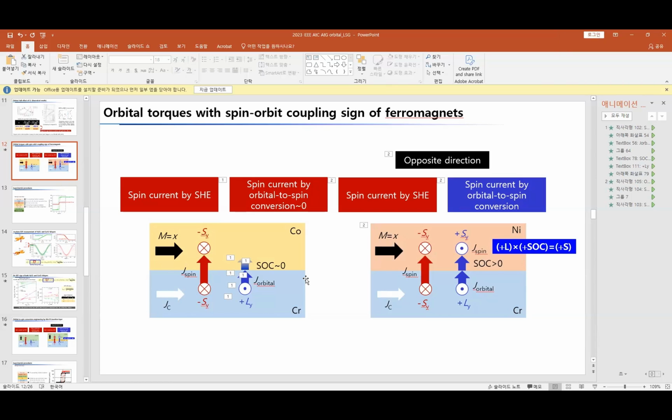I have a follow-up question. If you have a torque effect, how can you tell whether it is from spin torque or orbital torque? Actually, I can distinguish by the final sign of the spin-orbit torque. I precisely design the final spin-orbit torque: the conventional spin-orbit torque has a negative sign, but the one originating from the orbital Hall effect has a positive sign.